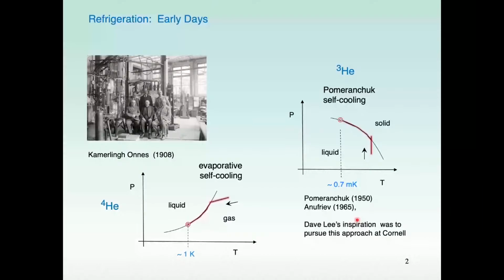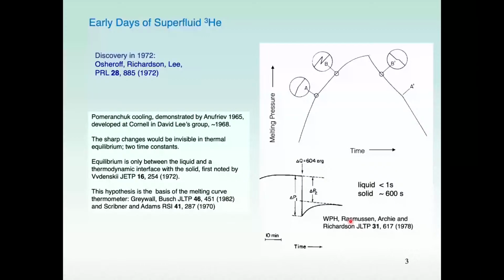The trace then of increasing the pressure and therefore obtaining cooling of some form wasn't precisely measured back in those days. This is in late 1971 and 72. But sharp changes along the pressure time trace indicated that something was happening, labeled A and B by Doug Osheroff. And if you apply a pulse of heat while the liquid and solid helium are on the melting curve, it's very interesting that you see two time responses. One is very short, associated with the liquid, and the other is very long, associated with the equilibrium established between liquid and all of the solid. There's almost 3 orders of magnitude difference in time.